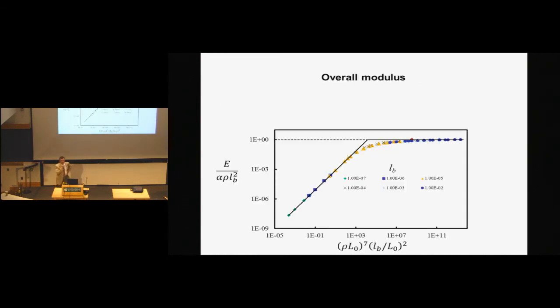Here is a really interesting result, and it tells quite a bit about the formation of these structures. It is a plot which has been constructed after running more than 80 types of networks with different parameters, L0, LC, and LB. For each set of parameters, we ran more than 20 replicas to get proper statistical information about these networks. No doubt, when you change the parameters of the network, you are going to get different elastic moduli. So the elasticity of these things is going to be very sensitive to L0, LB, and LC. But if you normalize the axes properly, you eventually get this master plot. So you basically collapse the data from 80 different sets of parameters to a master plot.